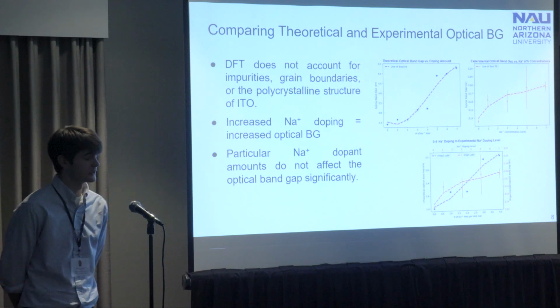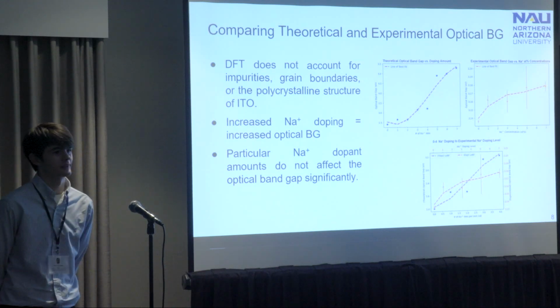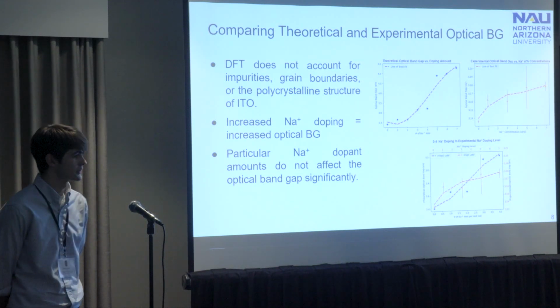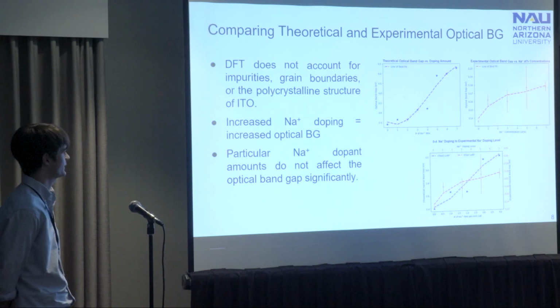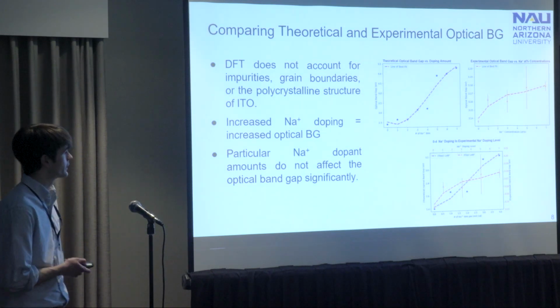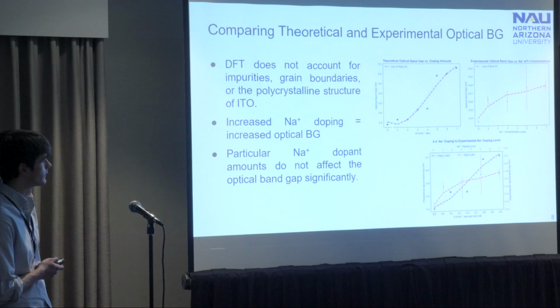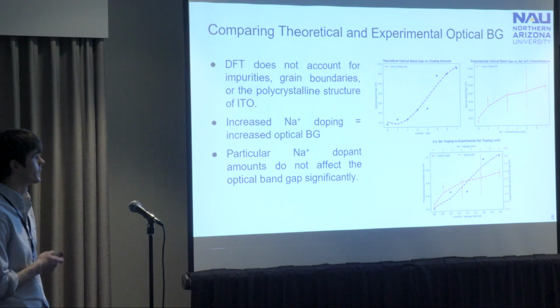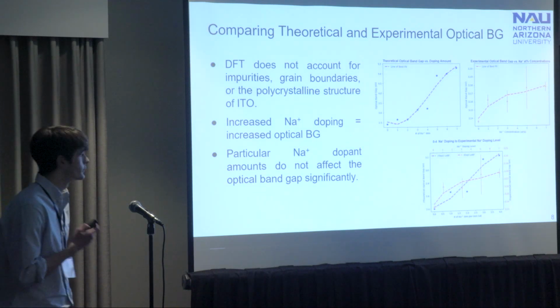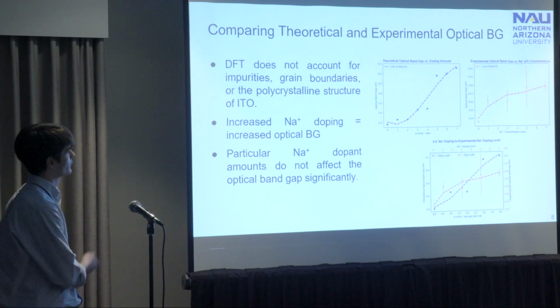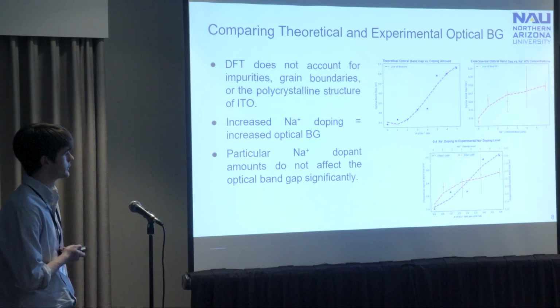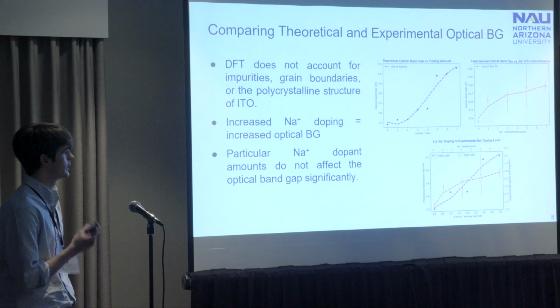However, what is similar, the first and most obvious one, is that as the sodium ion doping concentration increases, the optical band gap increases, thankfully. But a unique one is that if you look at the points specifically, not the line of best fit, for both plots, you can see that they increase in a stepwise fashion where they come in pairs. Thankfully, I use this as a basis of comparison when comparing theory to experimental data, and we have this bottom plot here where I matched those plateaus the best I could.